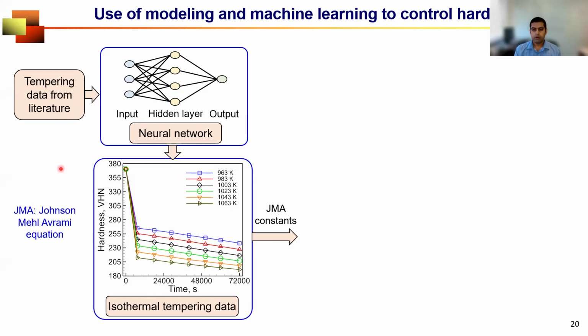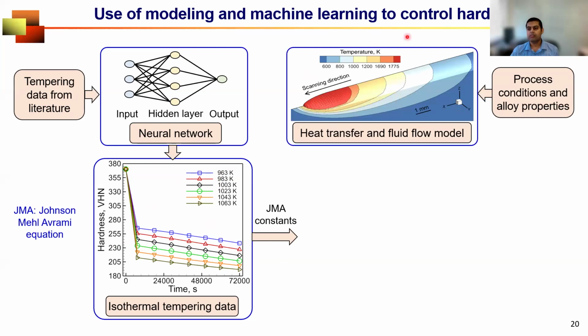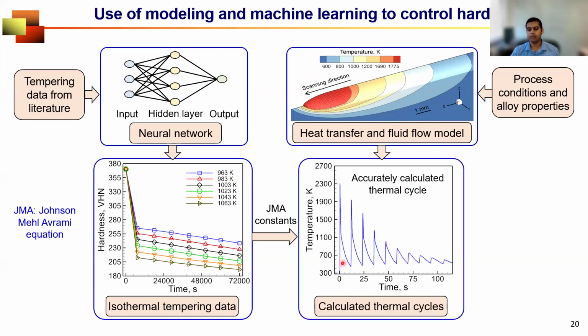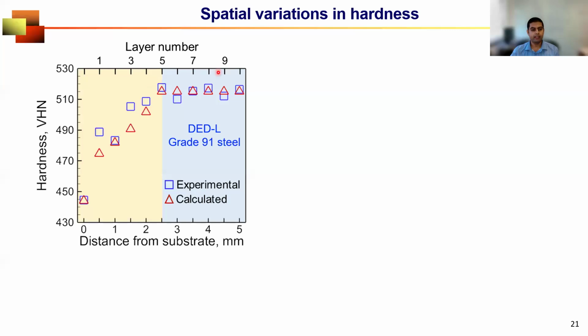On the other hand, the model that I was talking about can give you the temperature variations with time, multiple thermal cycles, repeated heating and cooling due to deposition of multiple layers and tracks. Now, the JMA equation is an isothermal phase transformation equation. So what we need to do is take that and integrate over the temperature variation with time. And that will give us the tempering kinetics as well as the hardness of the part. And it looks like this, where hardness is plotted for grade 91 steel part made by laser directed energy deposition with respect to the distance